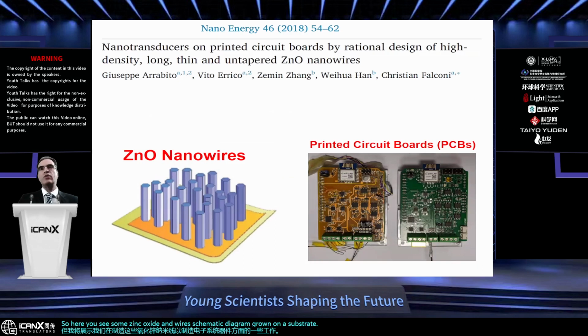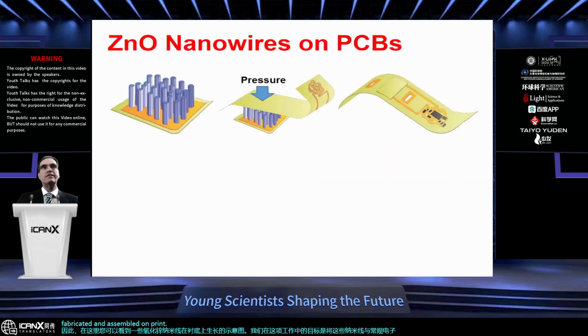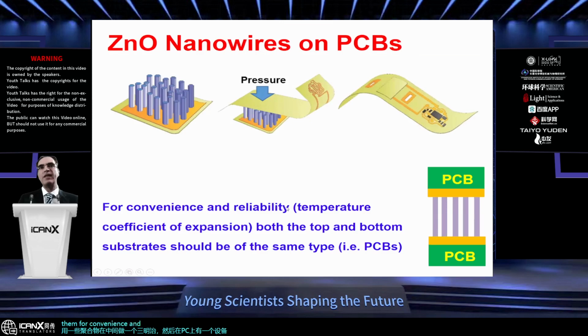And our goal in this work was to combine these nanowires with just conventional electronics that is fabricated and assembled on printed circuit boards. So this was our idea: to grow the nanowires and then to assemble the device by just placing another substrate with some polymer in the middle to make a sandwich, and then have a device on the PCB. Then, for convenience and also reliability, including to obtain matched temperature coefficient of expansion, all the substrates should be similar. And that means both PCB.